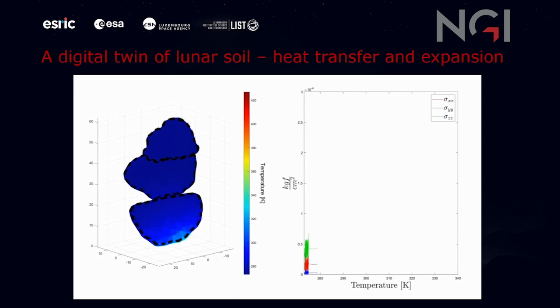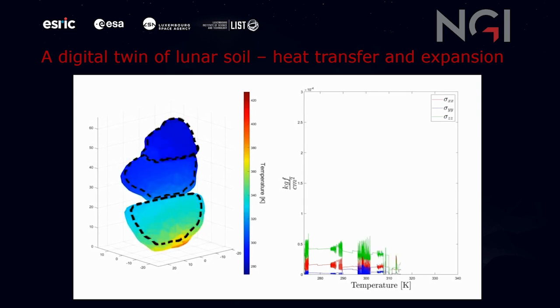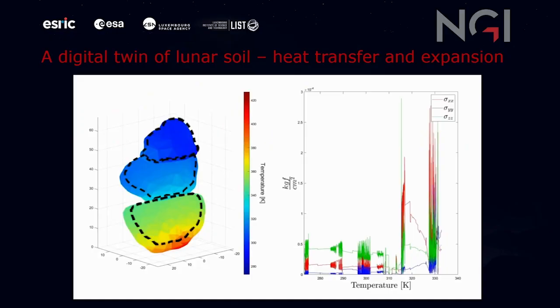Here we have a toy sample with only 3 grains, where we have combined 2 methods, the 3D LS-DEM, level set based DEM, that allows us to account for the grain shapes, and also finite elements that allow us to model the heat transfer, the time-dependent heat conduction among the grains. So this is a multiphysics and a multi-body problem. And we also include the capability of the grains to dilate, to swell due to the thermal changes. And on the right, we can see the stresses that these grain dilations or expansions create on the container's walls that cannot be seen here. So all of this can be done. Next.